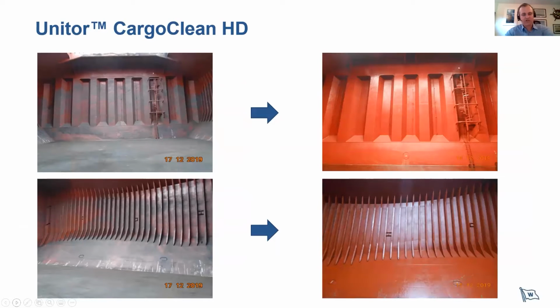To see this on a larger scale, we can now see pictures from a customer that has used Cargo Clean HD on coal stains. And we can see that they got very nice results on the cleaning task, but we can also see that the coating is intact and in good condition. So you can also have these kinds of results when performing the cargo cleaning.